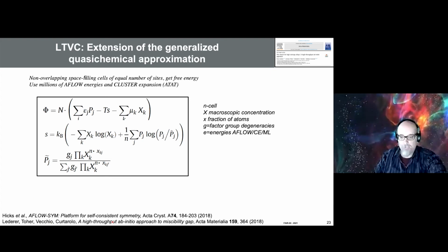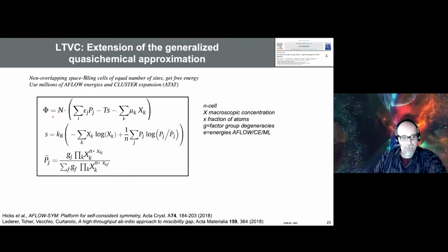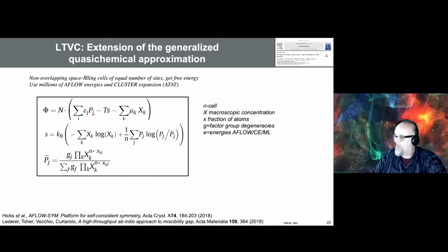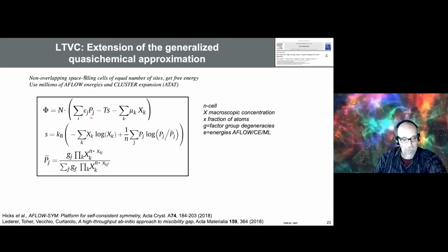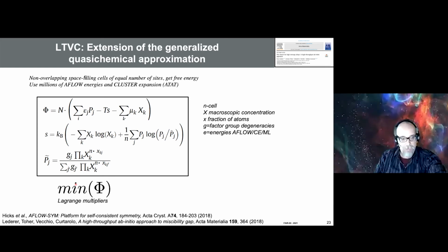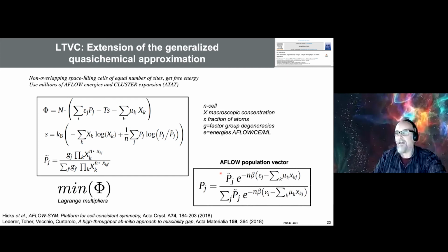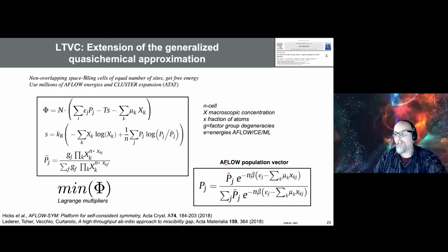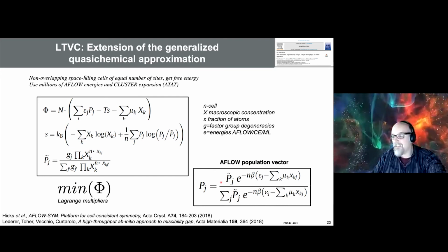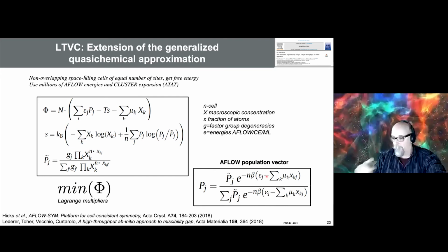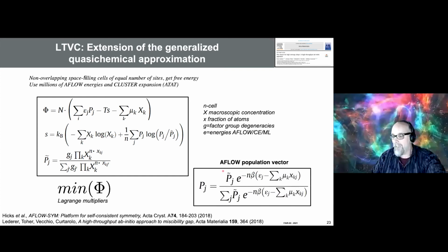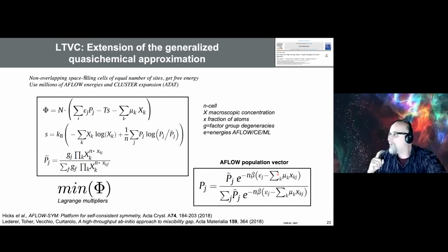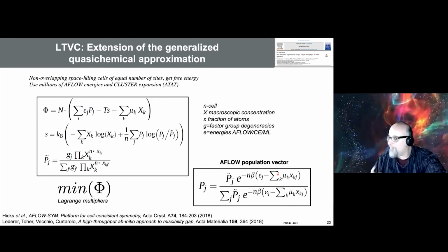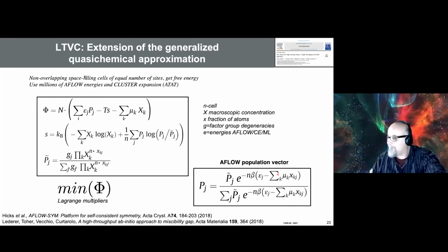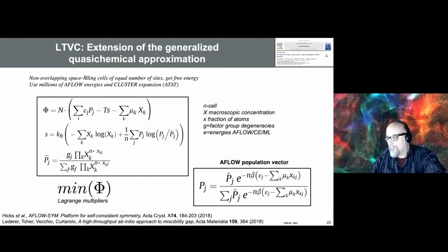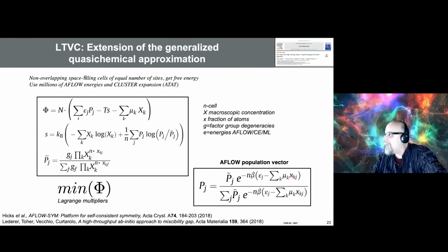So you can read this article, it's kind of obvious. Once you do this and you minimize this grand potential, and you have all this J calculation, there are millions of them, and you can get them online. You do it with Lagrange multipliers, and then you find that you pretty much have what is called the AFLOW population vector. This is exactly the P of before. Remember the P of before, with the normalization, it was a probability based on enthalpy. Now we have a probability based on Gibbs free energy, because we are removing the chemical potential. So it's exactly the same thing.